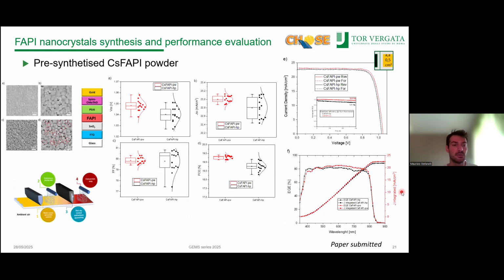Passing to the devices, we fabricated some cells with 0.5 square centimeters of active area, and here, even though the record devices have more or less the same efficiency, even if the cesium FAPI from powders is a little bit more efficient, the means of the full photovoltaic parameters show that the reproducibility is quite enhanced for the perovskite coming from the powder approach.